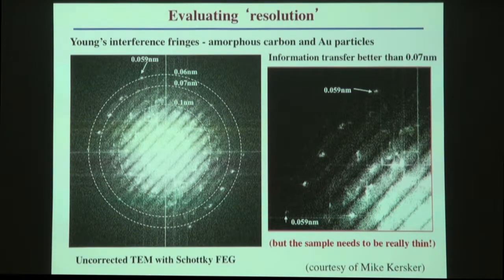The standard way was to take a diffractogram. The problem with a single diffractogram is you don't know what is real and what is noise. And so if you take two images, and then you displace them slightly sideways, and then get the diffractogram, you should see Young's fringes. So this is the so-called Young's fringes approach, where we have an amorphous carbon substrate and we have gold particles that give you the spacing in reciprocal space so you can calibrate the scale of your diffractogram. But then you have a problem. The sample needs to be really thin. There was considerable controversy about 5 years ago in the microscopy community because it appeared that 80 kV microscopes were too good to be true.